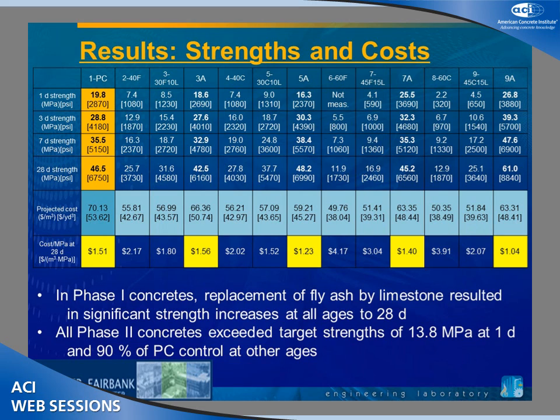The controls for the Portland cement mixture 1 are on the far left. And you can see the values at 1, 3, 7, and 28 days. What we were looking for was to get the 2,000 psi at 1 day. That was our target.